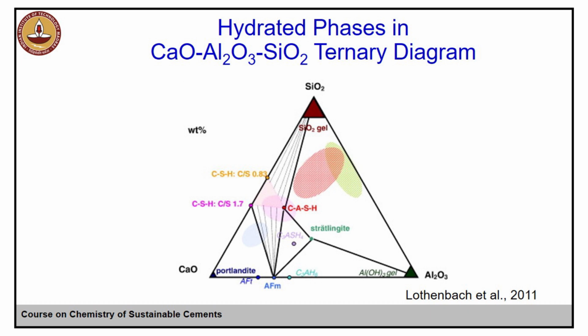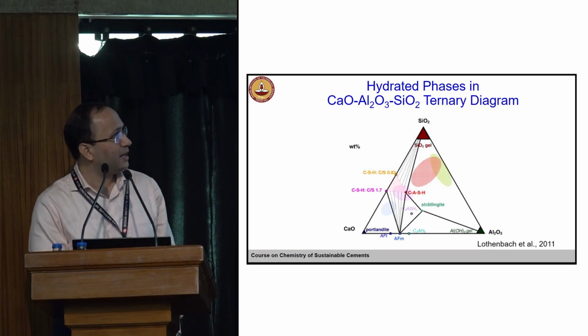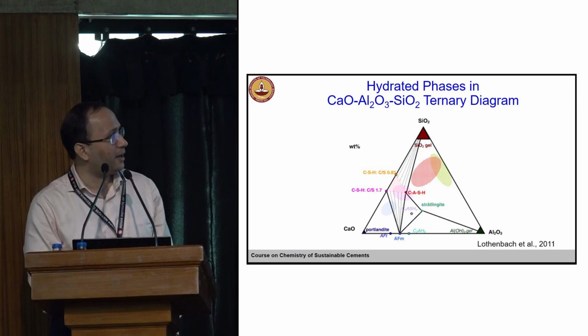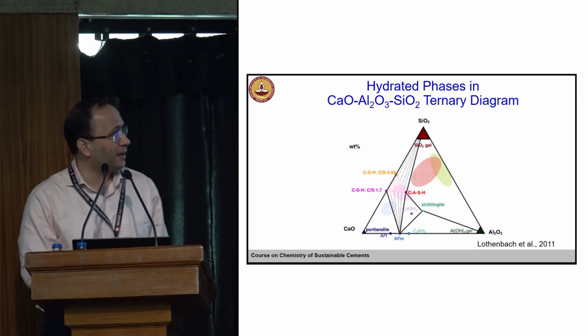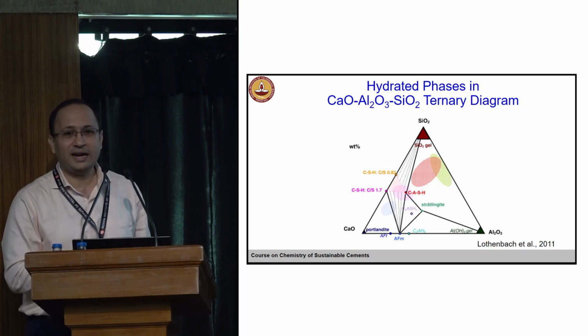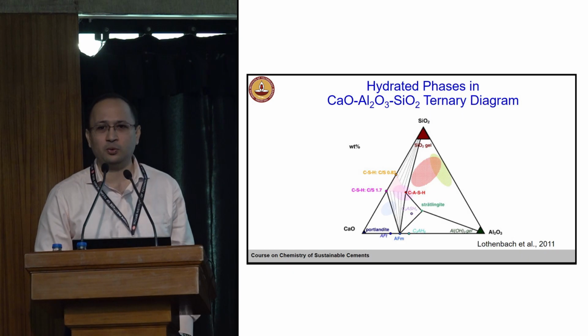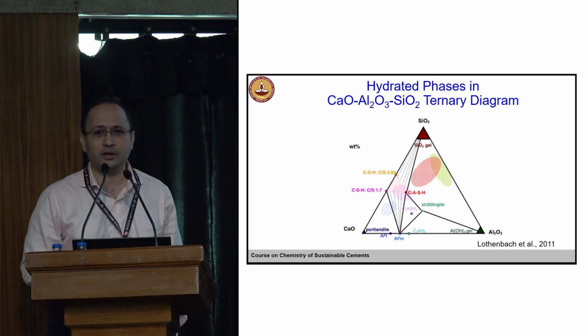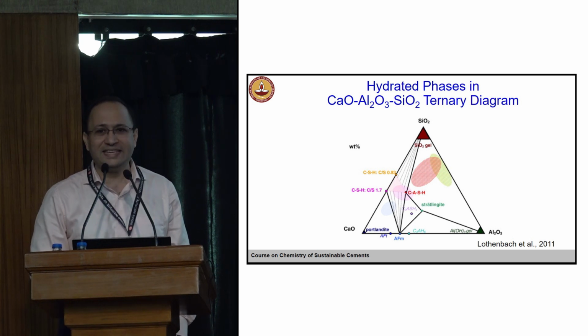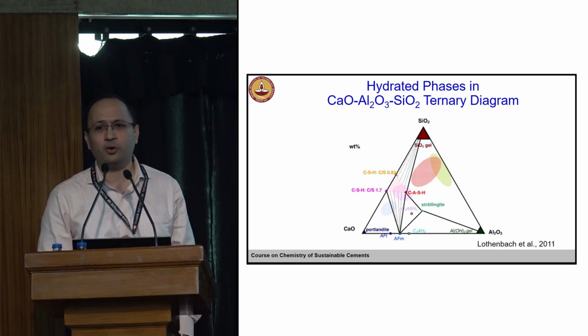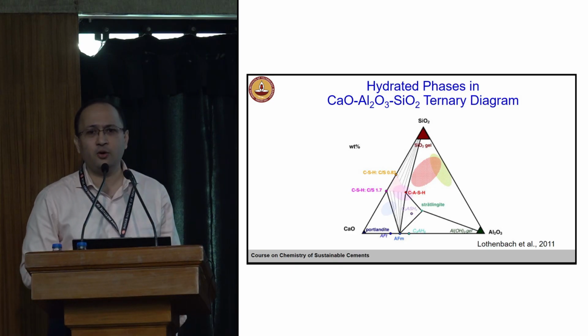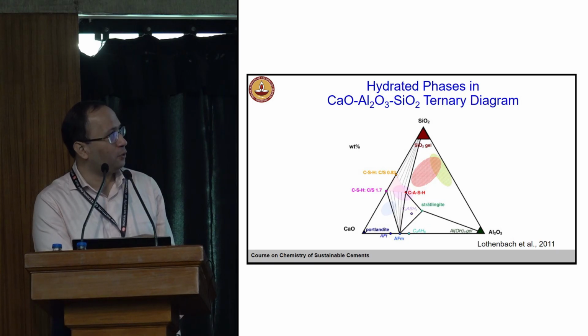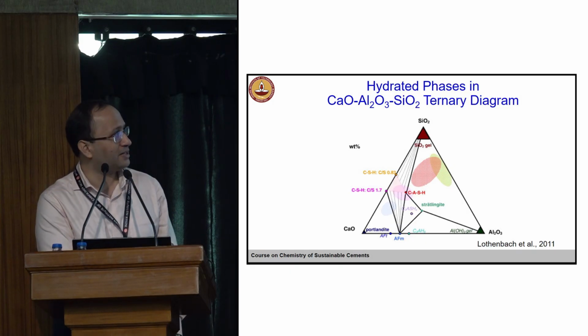So let's look at this ternary diagram and look at the different hydrated phases. Where will they be on this ternary phase diagram, right? So this is again a CAS ternary phase diagram, and you see calcium silicate hydrate. Now that 1.7, right, what Professor Shashank was referring to, is kind of an average figure for the calcium to silicon ratio of CSH, which is formed in hydrated Portland cement. Okay, it averages at around 1.7. But see, if you go towards this silica apex, your calcium to silicon ratio will reduce. So you have, let's say, 0.83 on this.